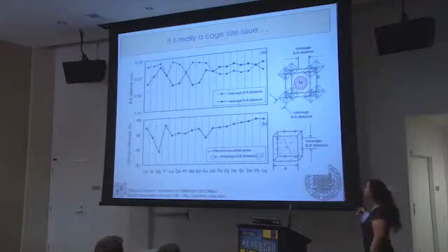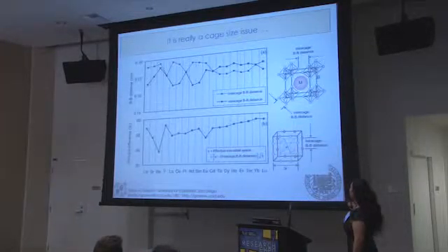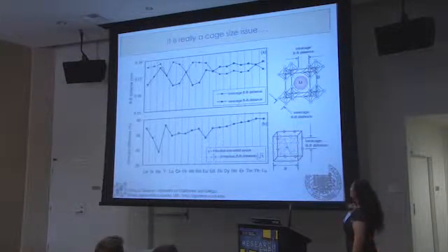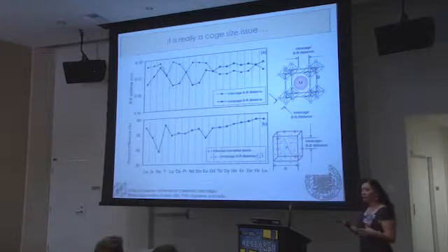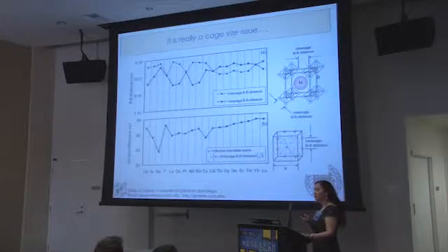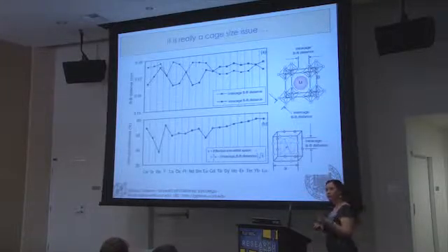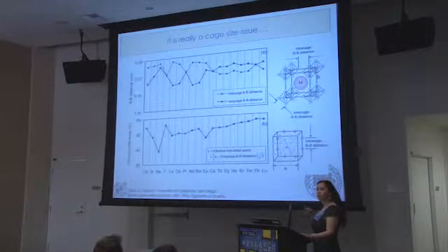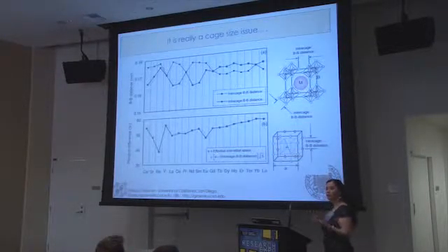The main interest in this material is that if you have an ion here that is typically a +3 valency, then that rare earth ion wants to donate 3 electrons to the conduction band. And 2 of those electrons actually go to the boron framework, because the boron framework is electron deficient by 2 electrons. So it needs to be stabilized somehow, and it is stabilized by the electrons donated by the rare earth ion. What that means is that you end up with 1 extra electron. That extra electron goes to the conduction band, and this becomes an electronic conductor.